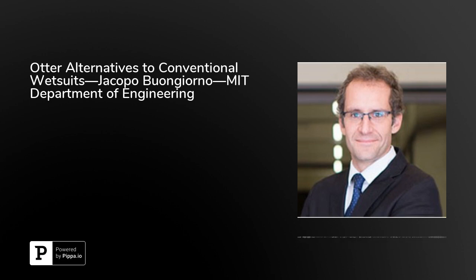In a normal wetsuit, what percentage of the outermost part of the wetsuit gets wet? Like, how deep does it saturate in? And is there anything to be gained there by having less of the suit saturate? Yeah, there is. The pores are relatively small, we're looking at things like hundreds of microns. Nonetheless, depending on the material, the neoprene itself, whether the material is laminated with a sheet of nylon or nylon-like material, you can have, as you just mentioned, penetration of water inside the pores. Of course, that's detrimental to the performance of the wetsuit.